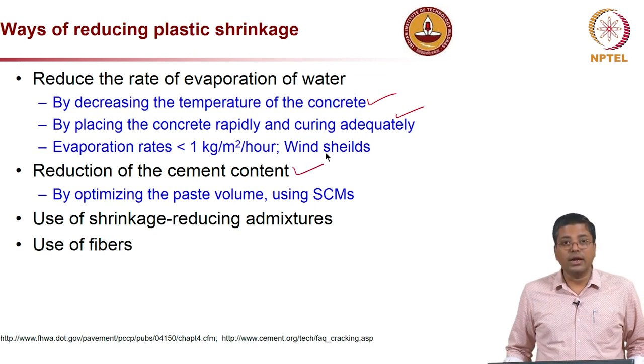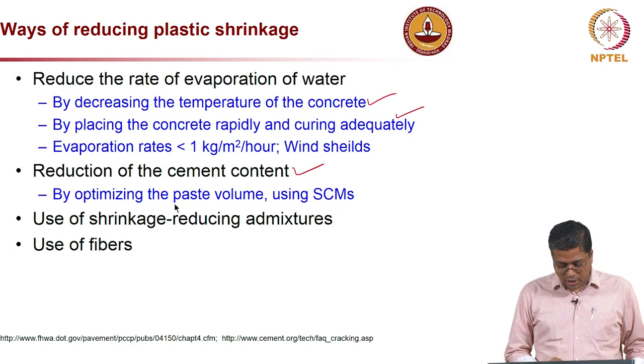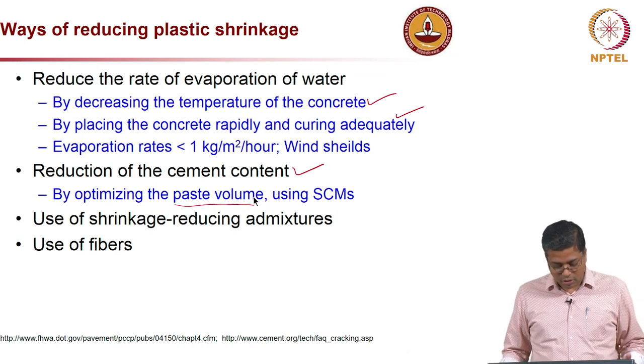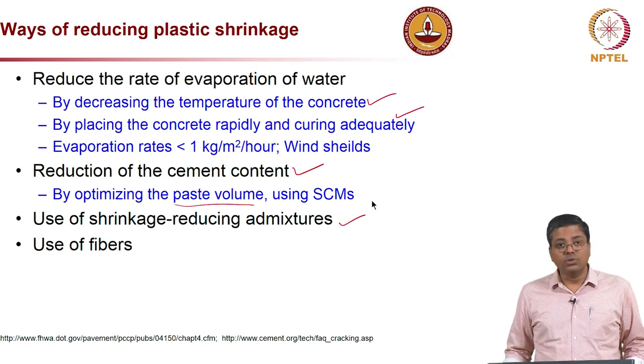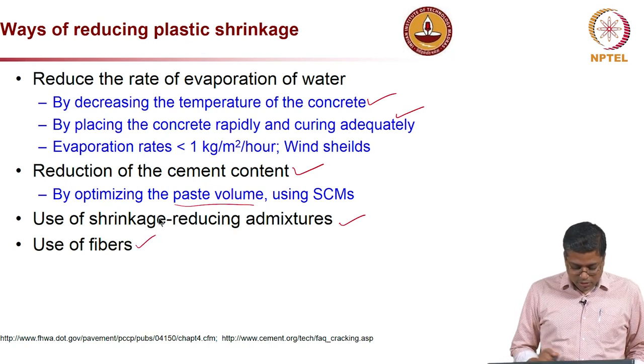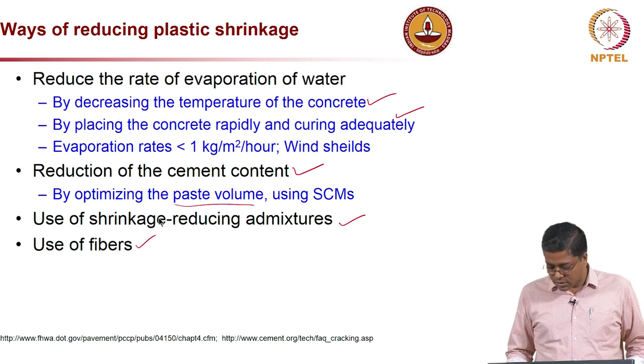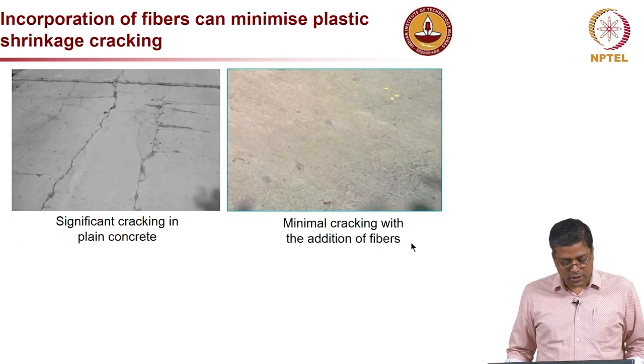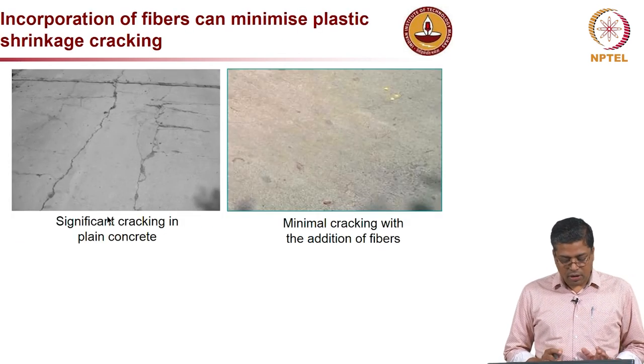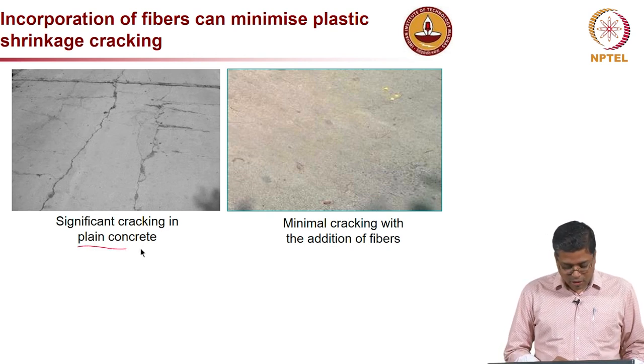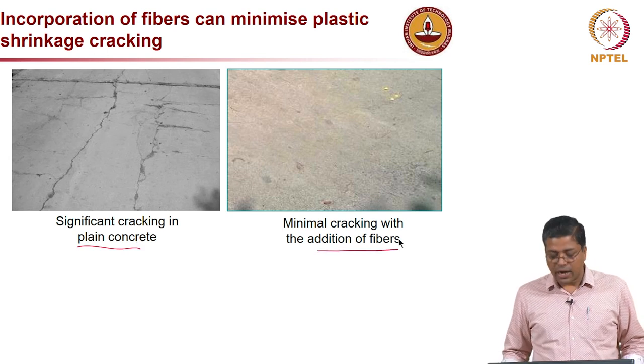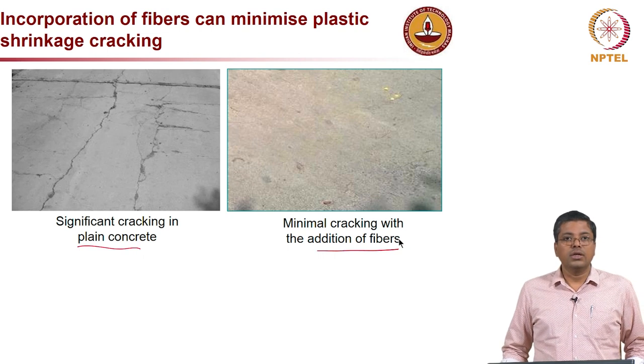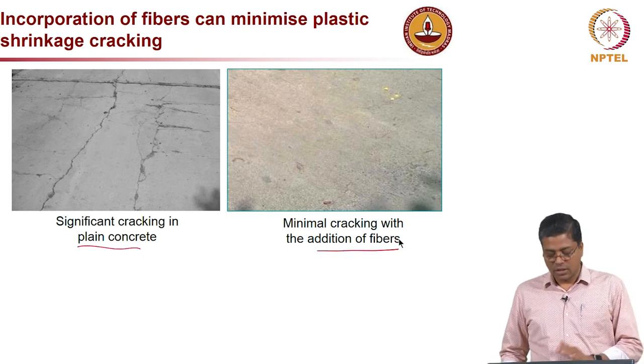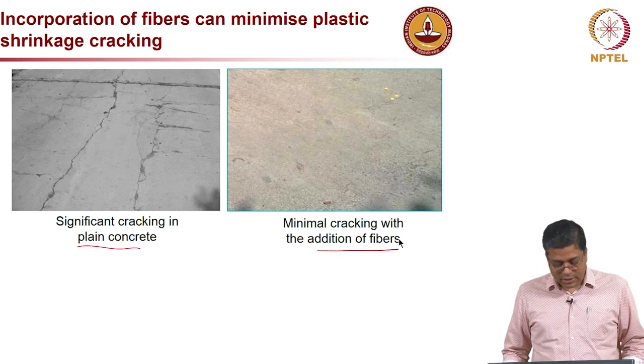And also we can go by reducing the amount of cement or optimizing the paste volume, especially by using supplementary cementitious materials like fly ash or slag, or those kinds of materials. Shrinkage reducing admixtures are also available, which can reduce the shrinkage, and the use of fibers is also helpful in reducing plastic shrinkage cracking. You can see here, this is an example of a concrete without fibers, or plain concrete, on the left side, and on the right side with the addition of fibers. Very clearly you can see the concrete on the left side has significant cracking, the one on the right side has much less cracking.